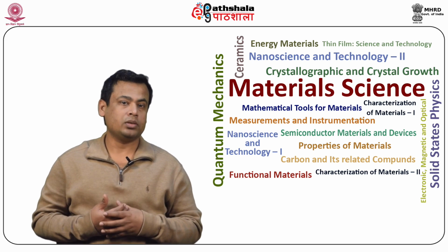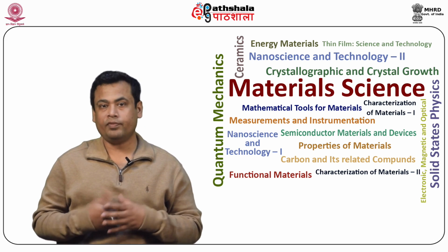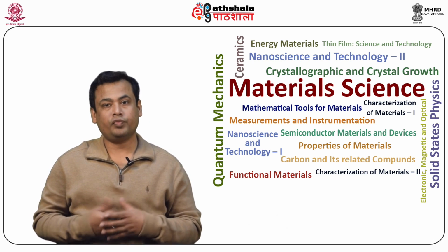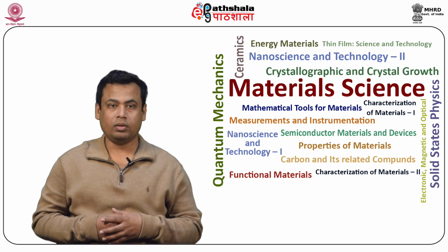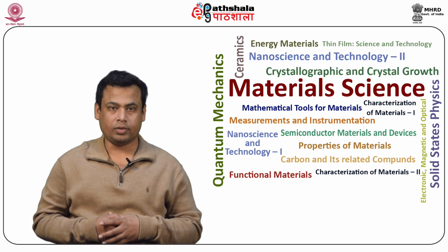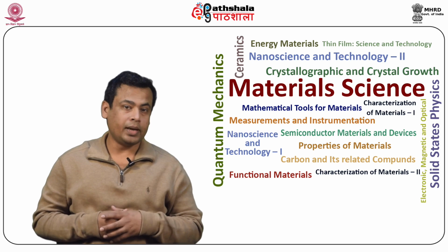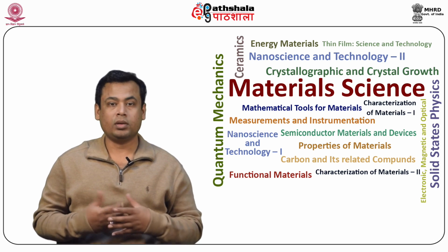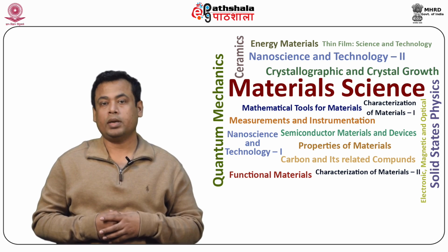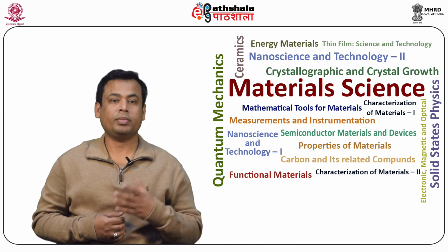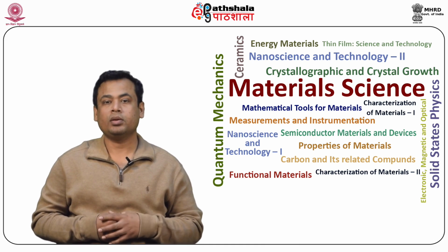The energies of aluminum K alpha and magnesium K alpha are 1.4866 and 1.25 kiloelectron volt respectively, which is lower than the energies of copper K alpha line, which is 8 kiloelectron volt, and molybdenum K alpha line, which is 17.44 kiloelectron volt, and normally used in X-ray diffractometry.